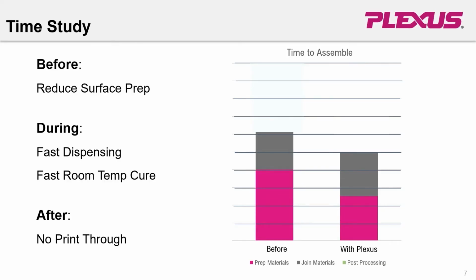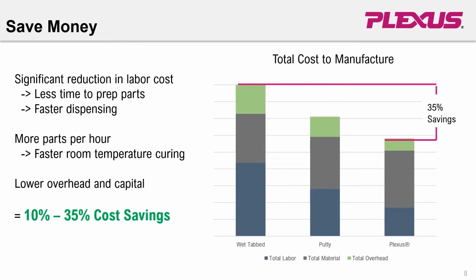So let's talk a little bit about process. Before, particularly with putties, in many instances, scuffing, particularly on gel coats or other areas, was needed to ensure good bonds. Well, Plexus can reduce or eliminate that. We can dispense quicker and cure quicker at room temperature, and then because there's no print through, there's no fixing parts afterwards.